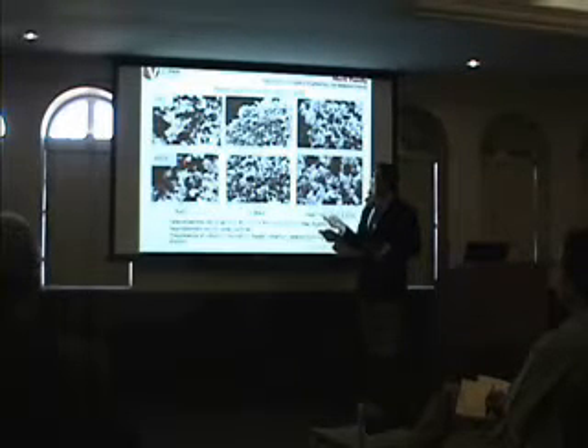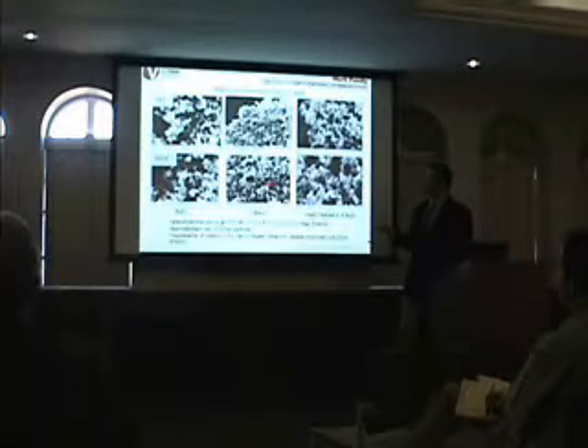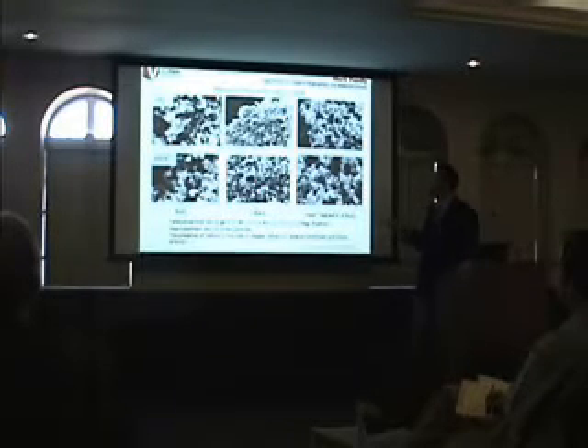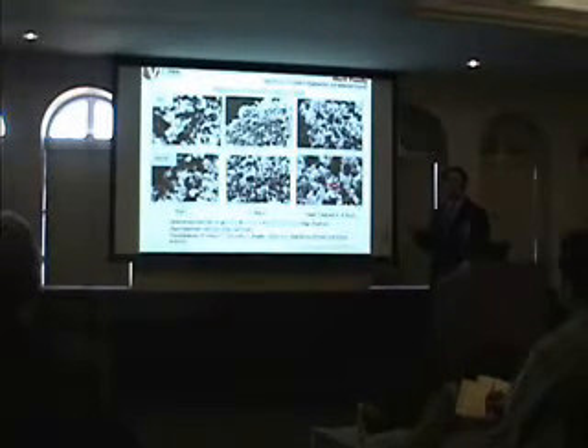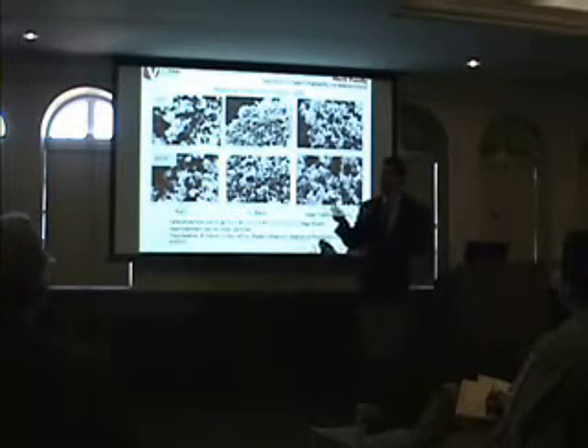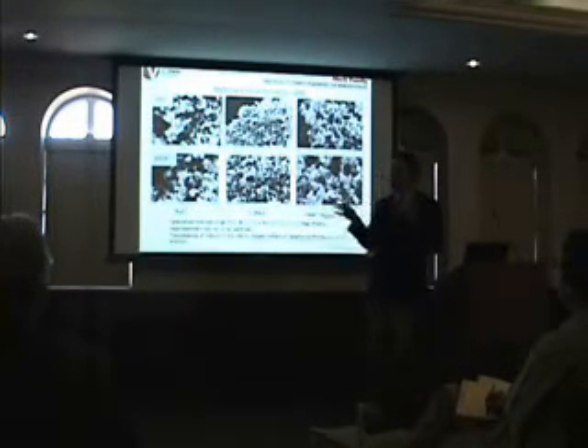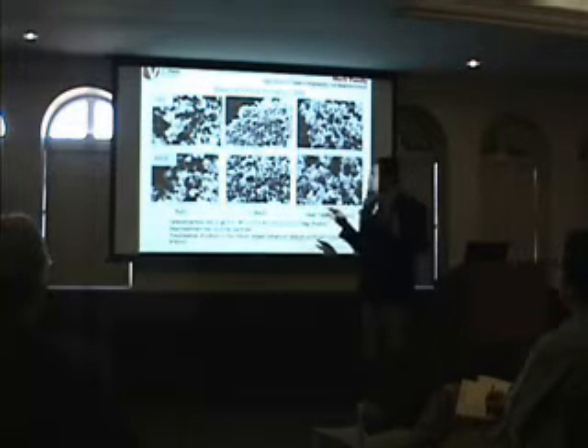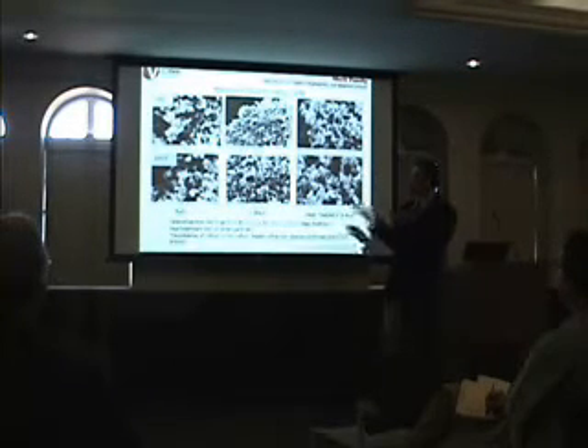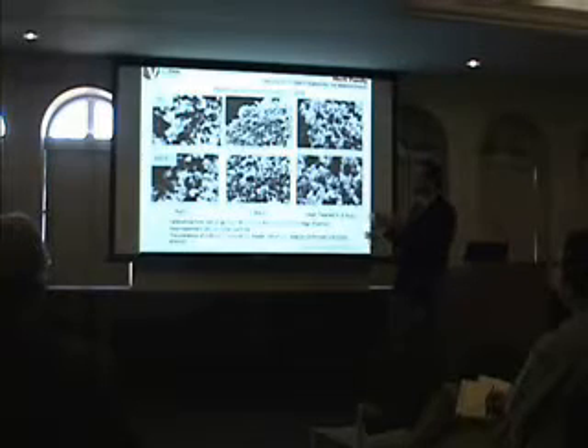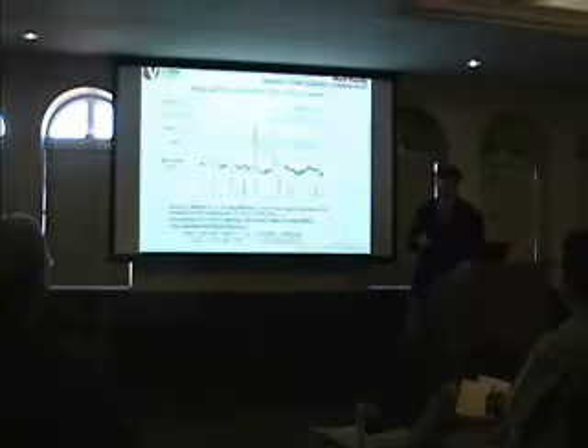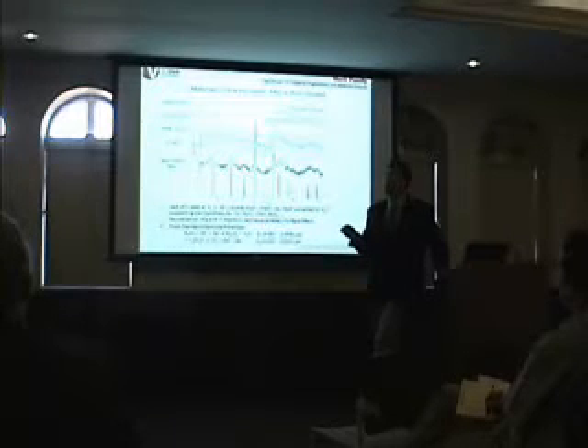So here's ruthenium oxide, this is SEM, 50K and 100K ruthenium oxide. Here's your iridium black, these are our 2 starting materials. And here's the heat-treated iridium, what we're calling an iridium-doped ruthenium oxide. And you can't really tell much from these SEM micrographs other than just looking at them and saying, okay, the morphology is about the same. We really can't talk too much about particle size and whatnot, but we could say they look similar. It doesn't look like anything is getting too different than the base material. So we were very happy with that.